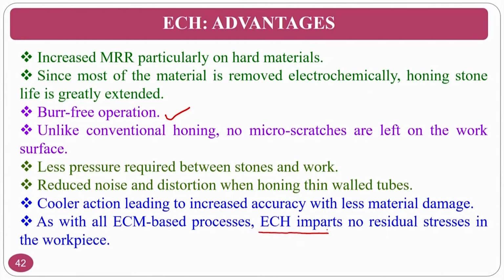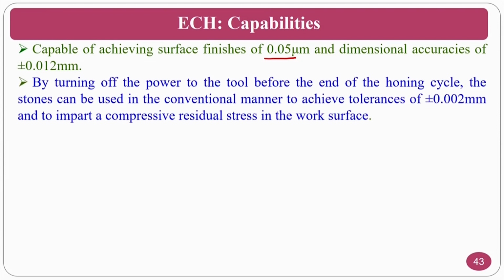Electrochemical honing imparts no residual stresses because the temperature is minimum. Okay. The capabilities: it can achieve surface finishes of 0.05 microns and dimensional accuracies of plus or minus 0.012 mm. By turning off the power to the tool before the ending of the hone, you can generate compressive residual stresses, and low tolerances can be achieved.